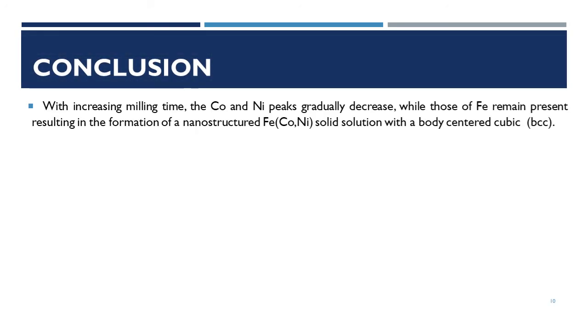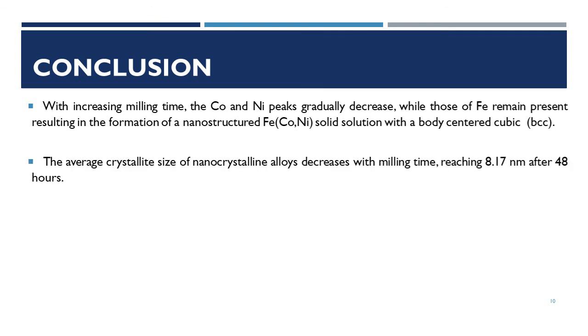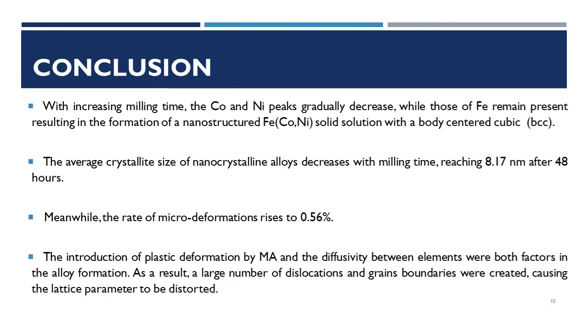Finally, as a conclusion, we can say that with increasing milling time, the cobalt and nickel peaks gradually decrease, while those of iron remain present, resulting in the formation of a nanostructured iron cobalt nickel solid solution with a body-centered cubic structure. The average crystallite size of the nanostructured alloys decreases with milling time, reaching 8.17 nanometers after 48 hours. Meanwhile, the rate of the microdeformation rises up to 0.56%.